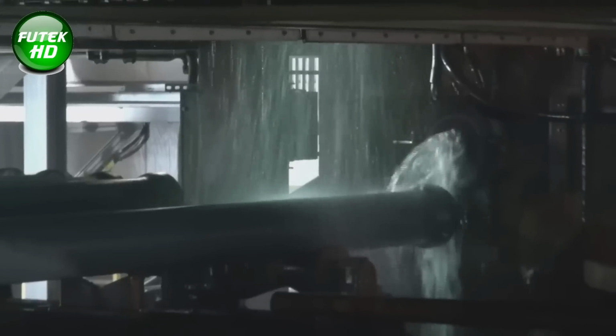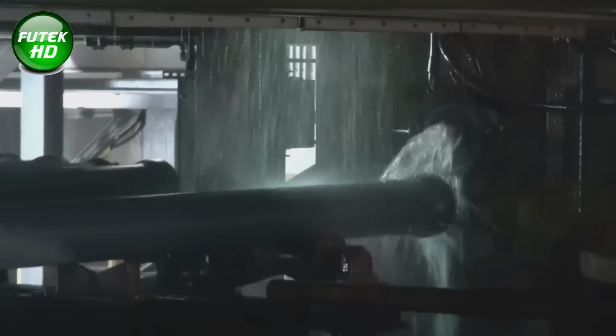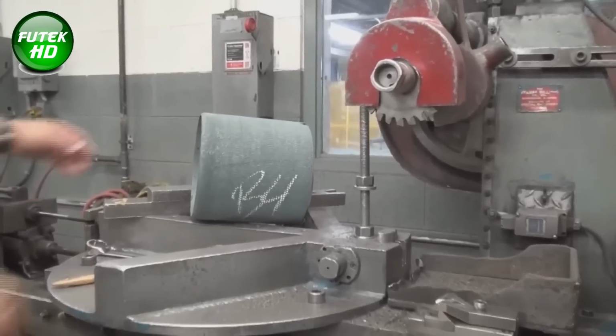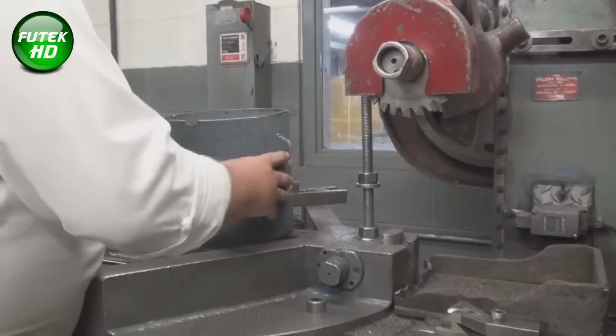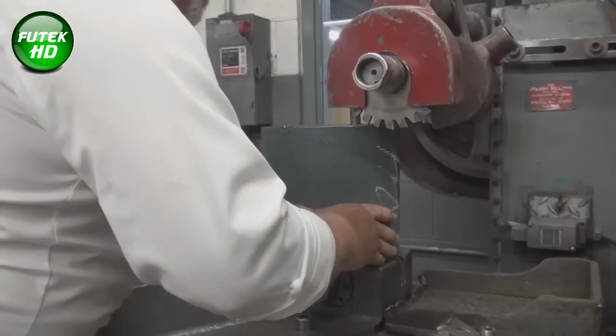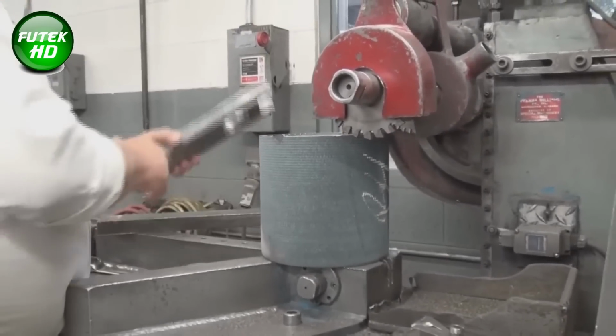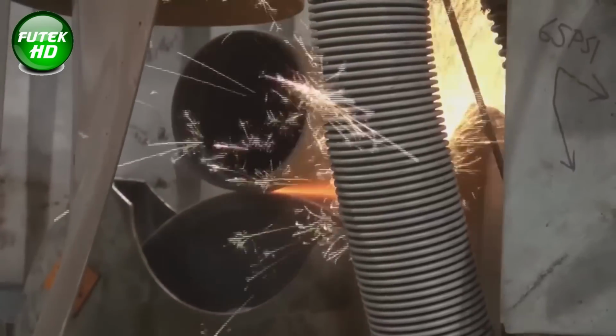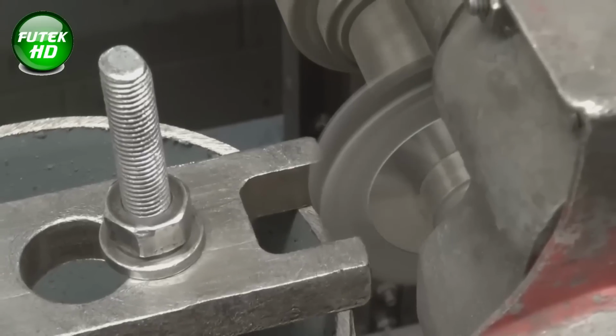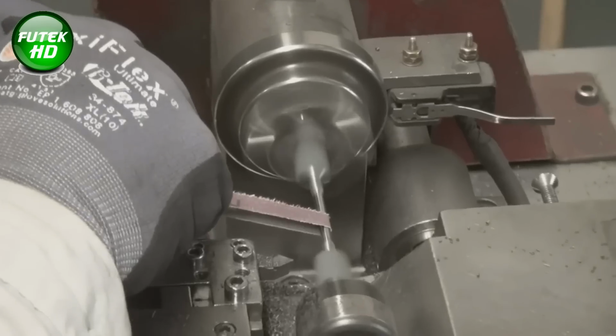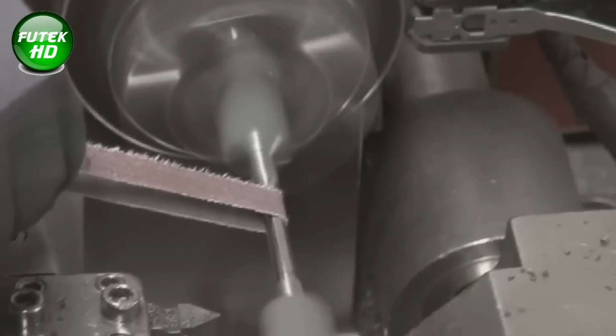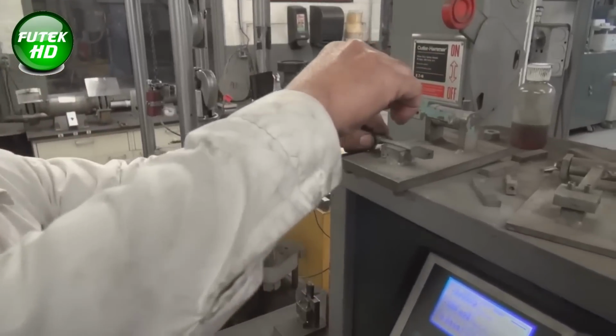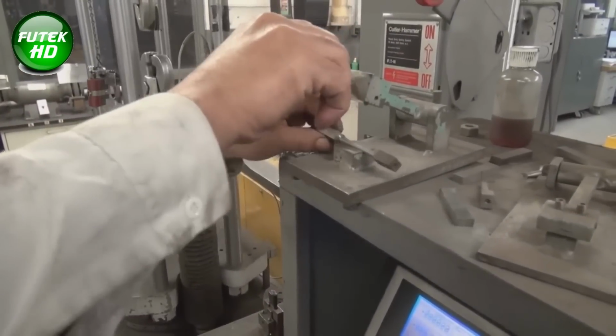Each pipe undergoes several mechanical tests to ensure strength and reliability. Hydrostatic testing: pipes are subjected to water pressure of 500 psi for 5 seconds to confirm structural integrity and the absence of leaks. Tensile testing: samples are cut from the pipe and tested for tensile strength, yield strength, and elongation. The tensile strength must reach at least 60,000 psi, and the pipe must demonstrate 10% elongation to meet AWWA standards.